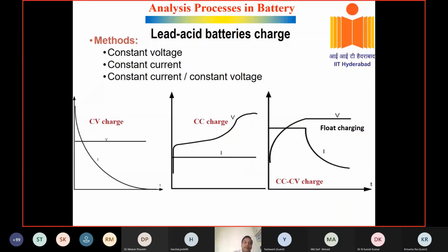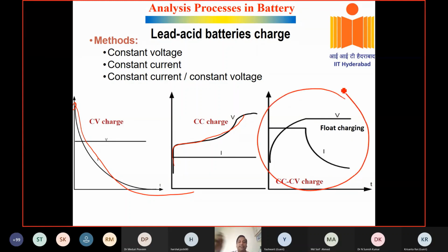So how do you do the formation? You can go for constant voltage charging. You can hold at 2.6 volt or 2.45 volt, and then your current will be very high initially, then it will reduce. I don't suggest this. There is another one all our students do, CC charging, constant current charging till a particular voltage is reached. In the lead-acid battery industry, generally CCCV charging is followed. Even in my postdoc and PhD times, I used to do CCCV charging to get full capacity. So what is CCCV charging?